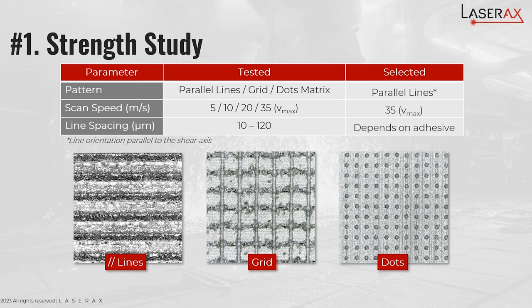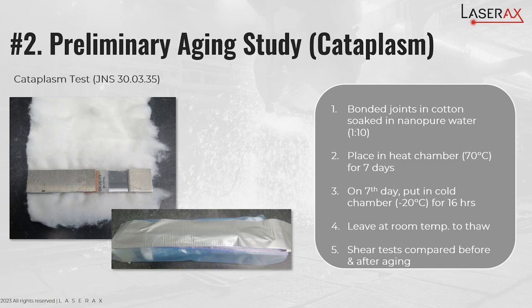Finally, we changed the line spacing, ranging between 10 and 120 microns. We realized that the best line spacing depends on the adhesive that you use, and we tested that over three different adhesives.